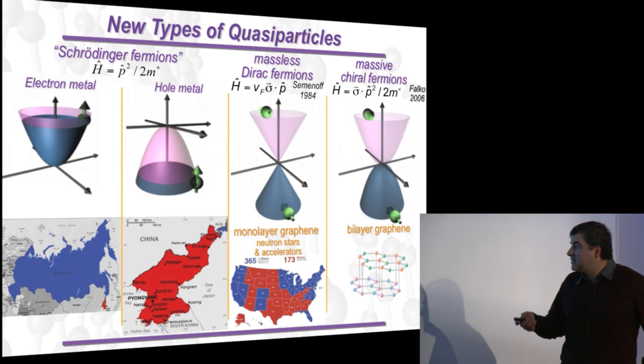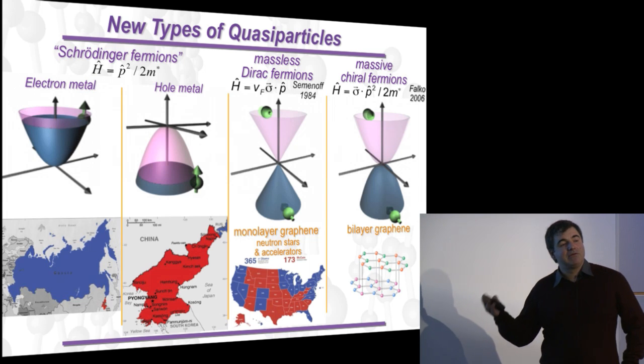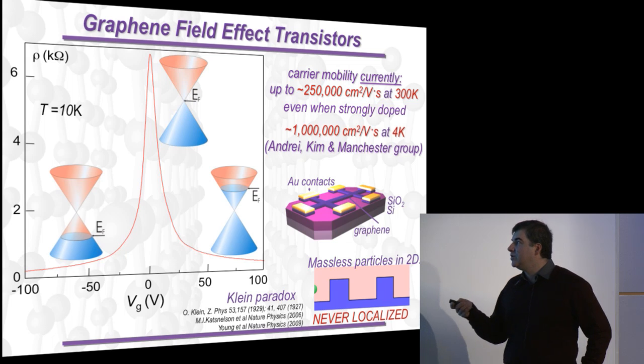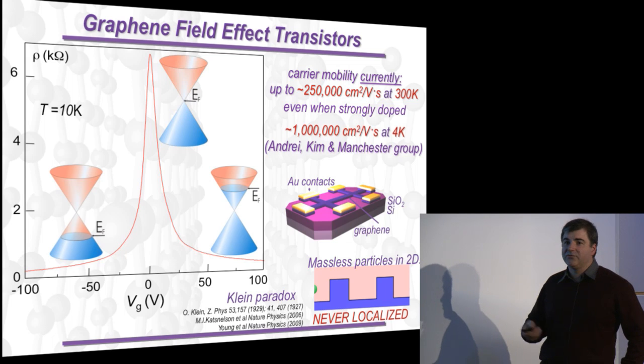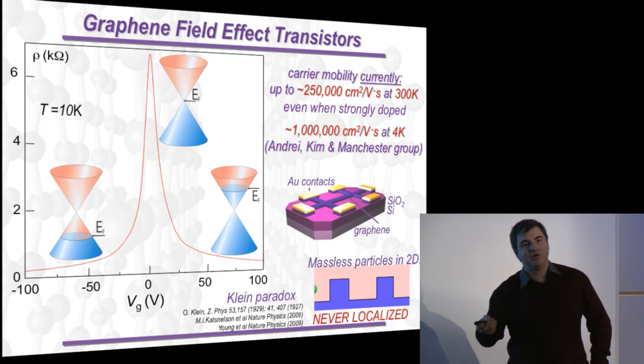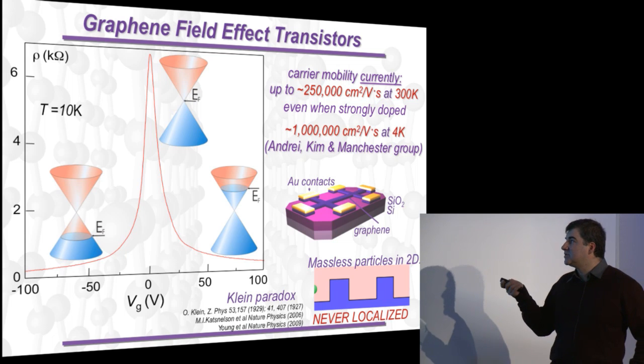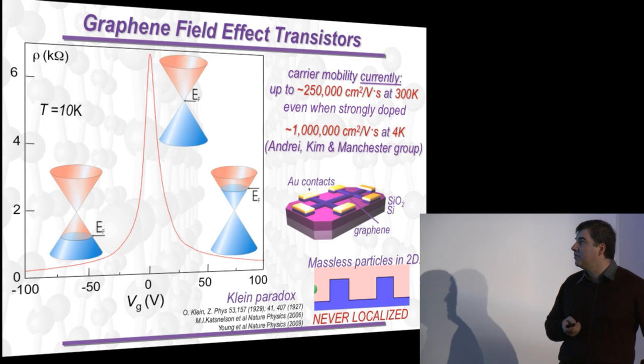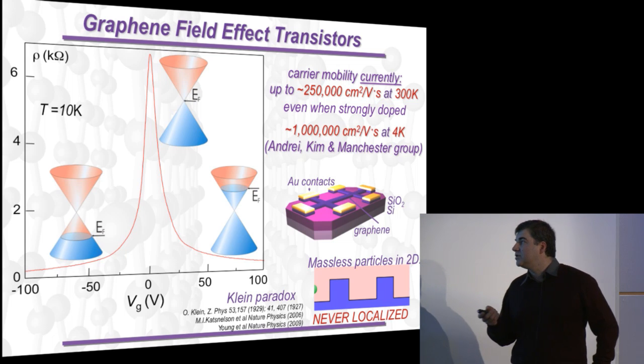So, this very special linear dispersion relation also guarantees us very special electronic properties, because those electrons can be converted into holes and back quite easily. They don't scatter as much as the electrons in any other materials. So the figure of merit for the amount of scattering, the mobility, which shows you how fast electrons travel through the crystal, is extremely high there. At room temperature it is about a quarter million, and at low temperature it is a few million.